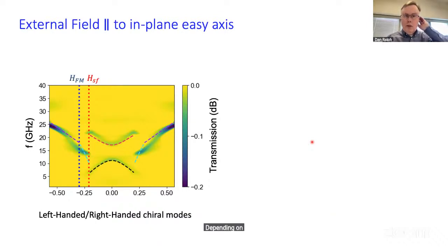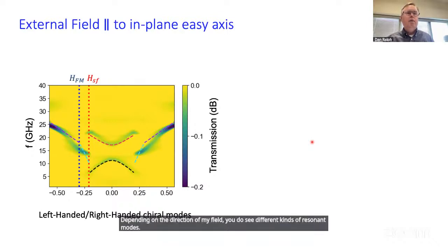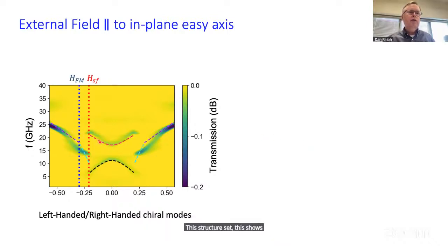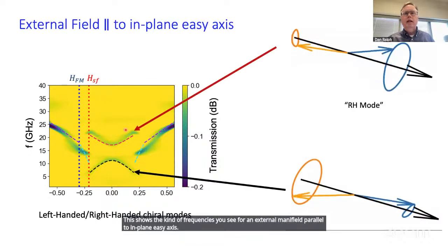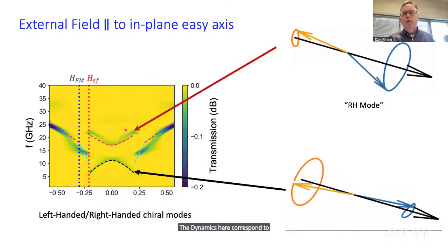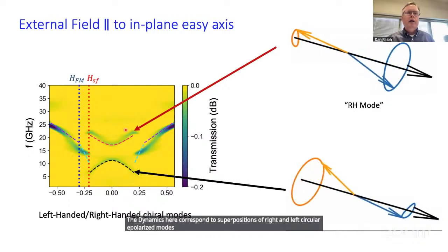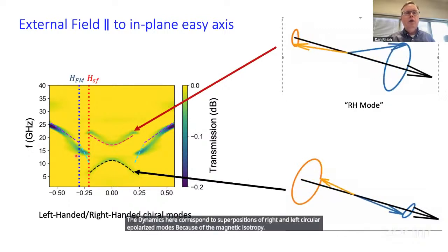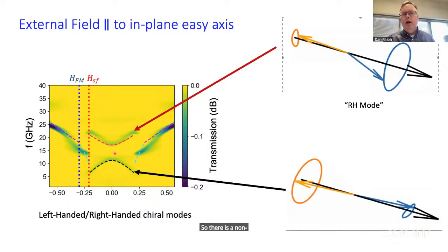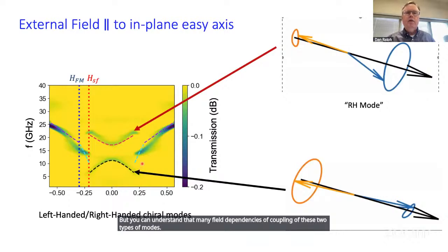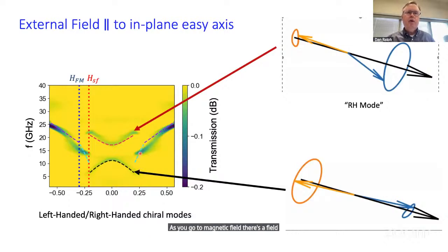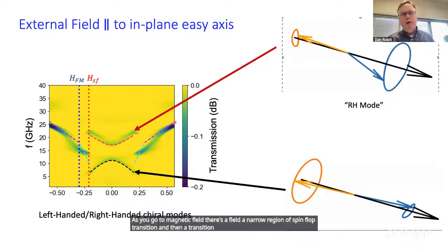Depending on the direction of the magnetic field, you do see different kinds of resonant modes. This shows the kind of frequencies you see for an external magnetic field parallel to the in-plane easy axis. The dynamics here correspond to superpositions of right and left circularly polarized modes. Because of the magnetic anisotropy, these modes are coupled, so there is a non-zero gap at zero magnetic field. But you can understand the magnetic field dependence as a coupling of these two types of modes. As you go up in magnetic field, there's a narrow region of spin flop transition and then a transition to a fully parallel alignment of the magnetic axis above about 0.3 Tesla or so.